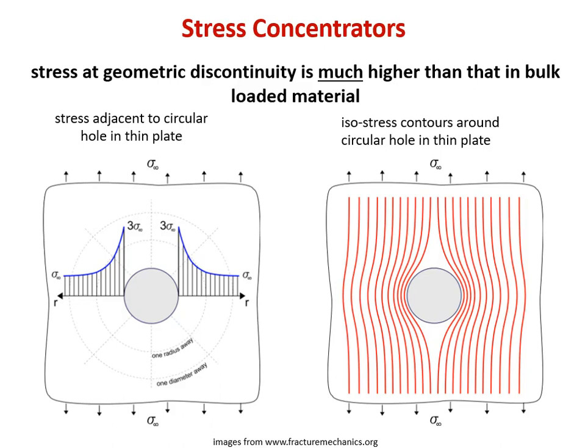So a stress concentrator is basically described as the stress at a geometric discontinuity that is much higher than in the bulk loaded material. So if you have a stress sigma infinity on an infinite plate, you have a huge plate of material, say in a pressure vessel, and you're yanking on it and it's enormous, and you have a small hole drilled through it, and you want to know what the stress state is immediately adjacent to that hole, it's going to be 3 times higher than the average stress that's being applied to that big semi-infinite plate. 3 times.